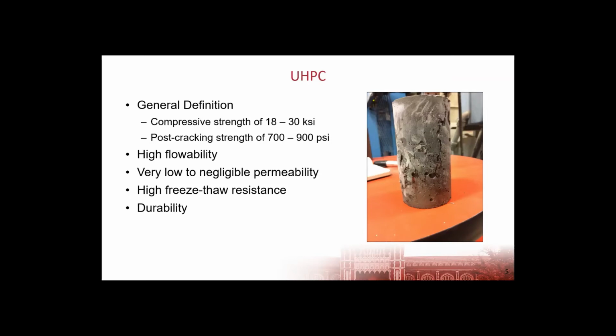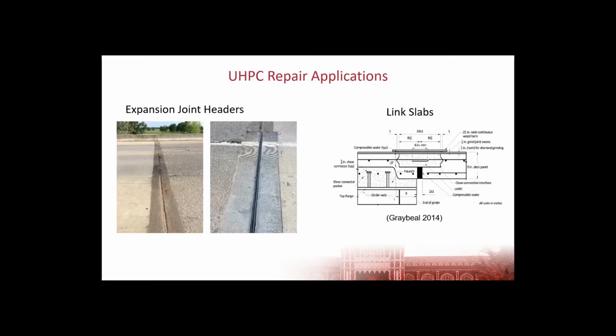But it also has a very low to negligible permeability, high freeze thaw resistance, just an overall great durability, which can help us to repair some of these damaged regions and to encapsulate them, to prevent further damage in the future. So in terms of what has been done in the past relative to UHPC repair and rehabilitation, within Oklahoma, we've done some study on expansion joint headers and actually done some field implementation using UHPC to repair around the expansion joints, which was kind of the motivation of this project.